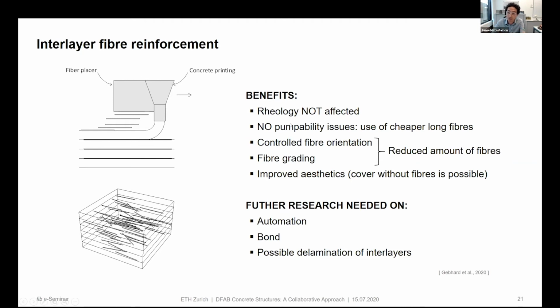And this has some benefits, so we don't affect rheology, or so we can use long fibers because we are not pumping the fibers, and we can grade the fibers and place them only when they are needed and in the orientation we want. And we are still working on this approach because it's not automated at the moment, and I think we have to figure out if we put a lot of fibers in an interlayer, maybe we have some negative effect that we don't have if the fibers are mixed in the concrete.